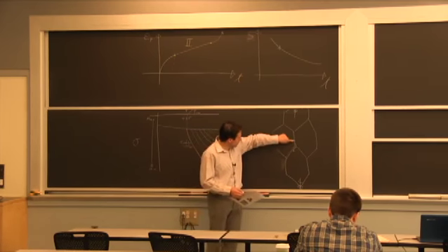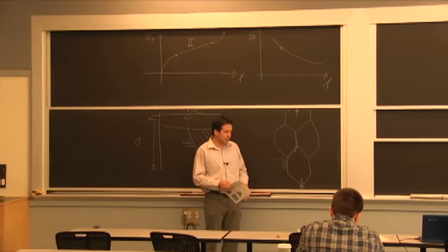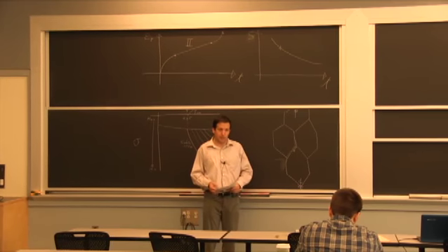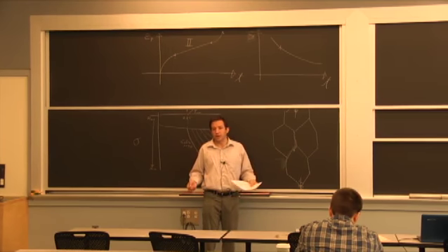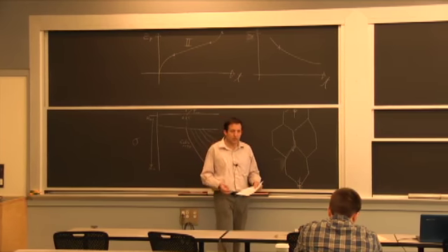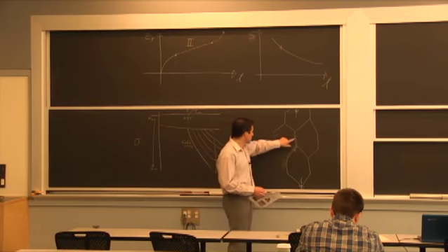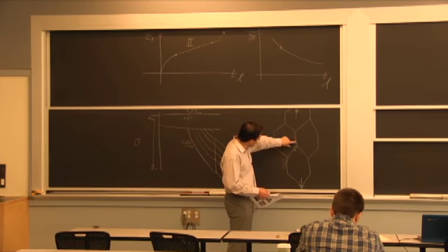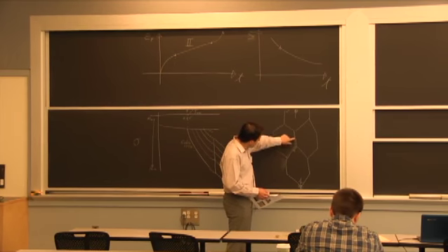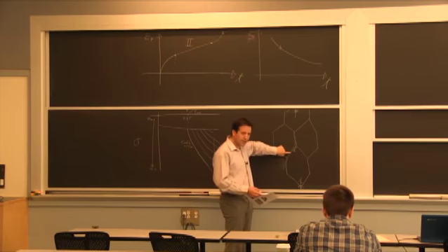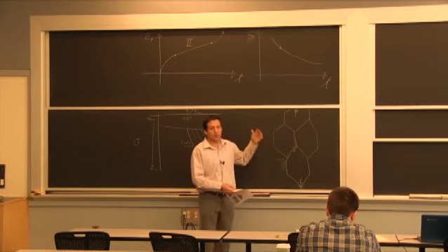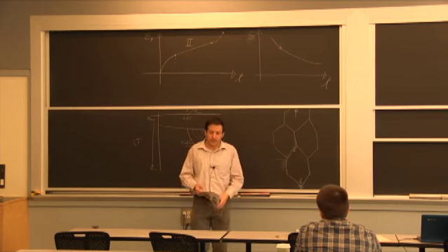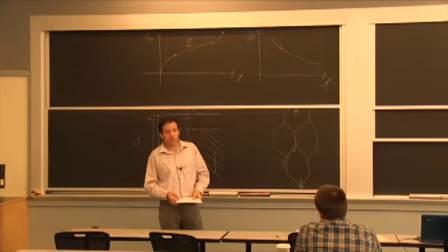But in the grain boundary, you have availability of space. It's not perfectly organized, so there's more space for the movement. So if I start moving atoms randomly, they go back and forth, then they get here, they realize there's more space, so eventually your grain will elongate. And that's how you get your permanent deformation in this regime of creep.